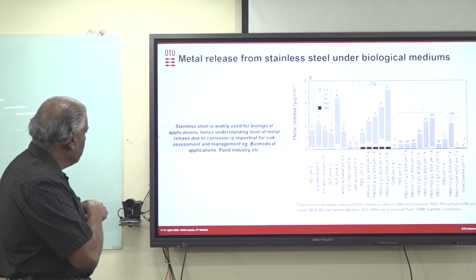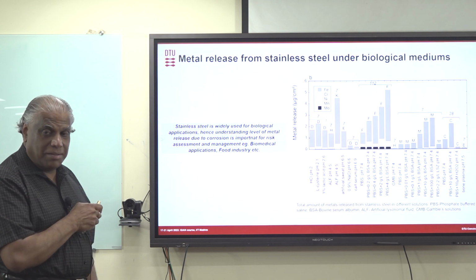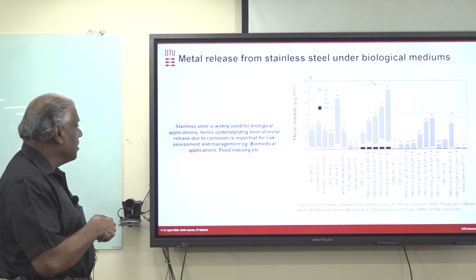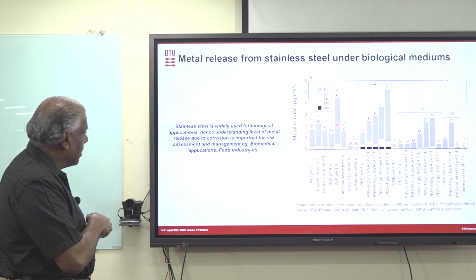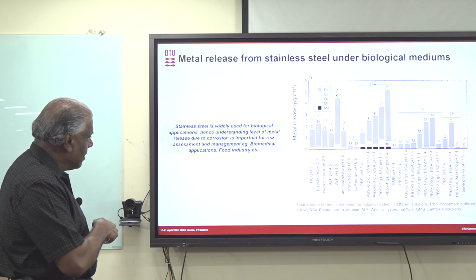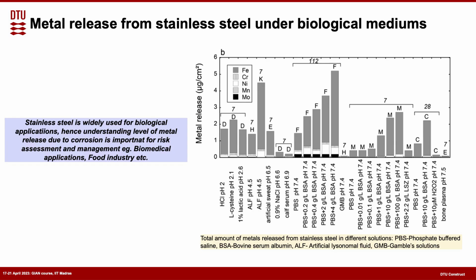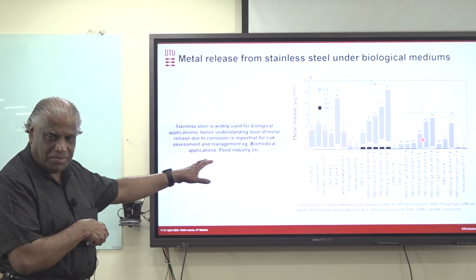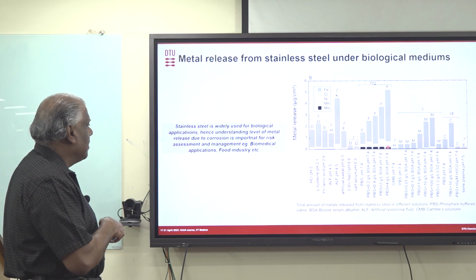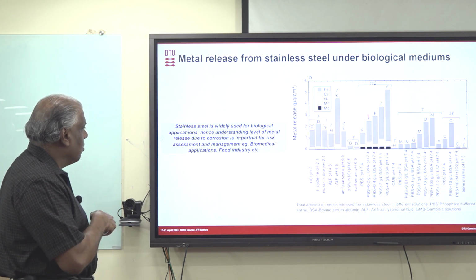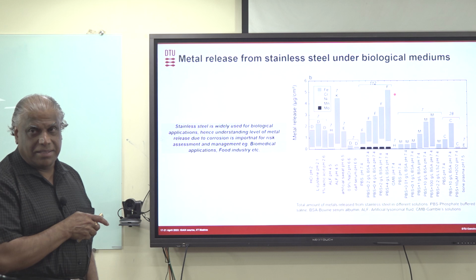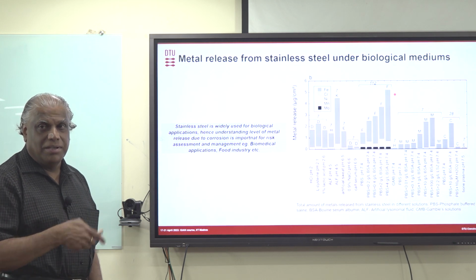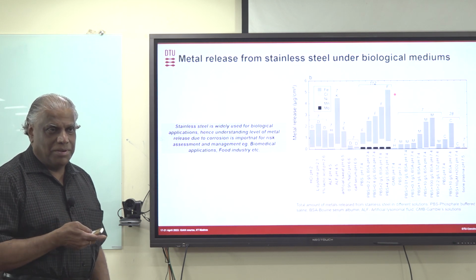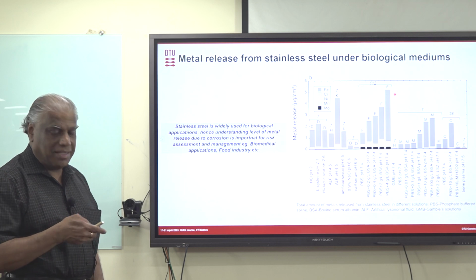Most of the time when they use stainless steel as an implant in the body, people get allergy. That's because of this nickel release. So you can see that in some of the solutions there is higher nickel release. We don't go into that detail, but we can look probably specifically at the chemistry of that solution. But there is nickel release. Almost all over there is a nickel release. And that's a worrying thing actually, because nickel release causes problems biologically, because it causes a lot of allergy.